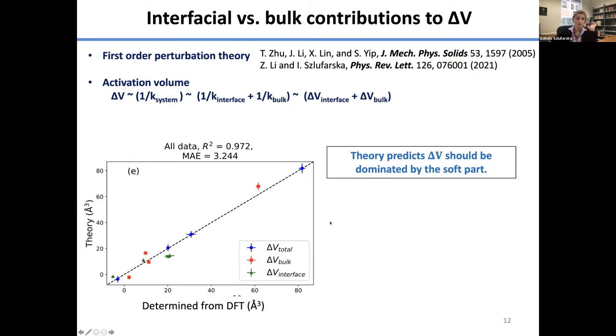So first of all, we have developed a theory to be able to predict or explain this activation volume. This is a theory based on first order perturbation theory, details in this paper. I'm not going to go into the detail, but here's the gist of it. The activation volume, or mechanochemical coupling, is inversely related to the stiffness of the system. Now the stiffness of the system can be broken down into different components, here interface and the bulk. So what that means basically is that the softer part of the system, in this case the bulk, is going to dominate the mechanochemical coupling. So you have a material that has different parts. The softer part is what's going to control the mechanochemical coupling at the interface. And it could be the bulk, right? So you can ask, what materials will have that, right? Because typically we're thinking of the interface molecules being fairly soft and the solid being hard.